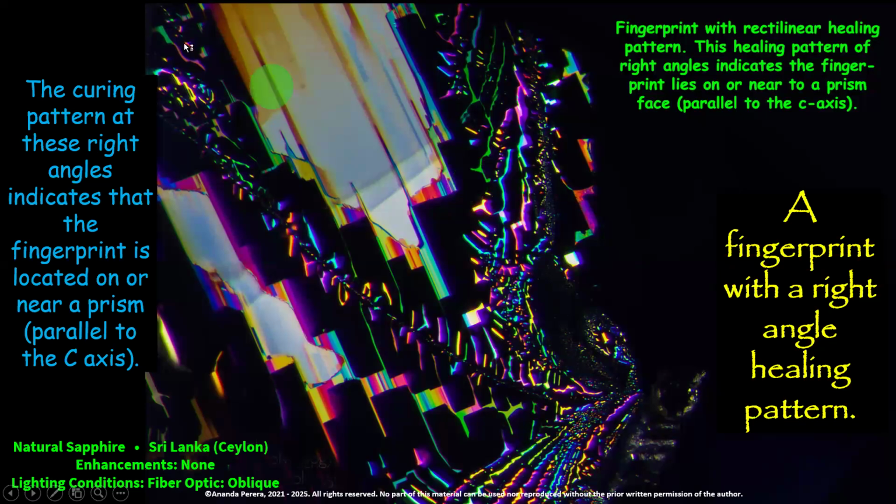Another fingerprint here. But all the shapes here are rectangular. So it is parallel to the C-axis. The prism face is parallel to the C-axis. Then it creates a beautiful fingerprint like this. Right angles are there. All the shapes here are right angles. So a fingerprint with the right angle healing pattern